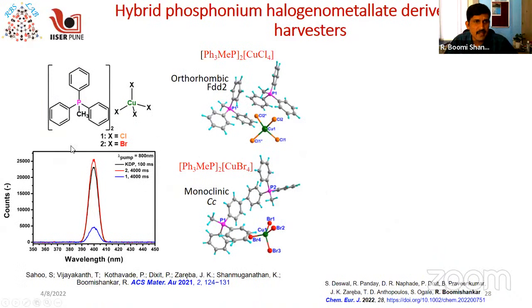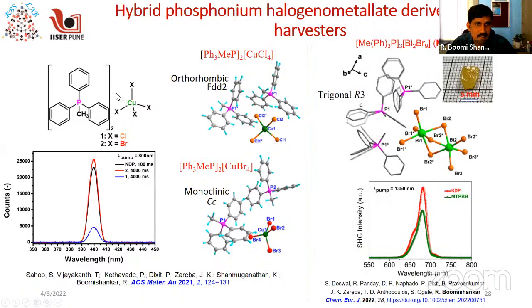and we then tried to use the potential of this system for various other anionic counterparts. So we use the same cation and use different anions. In this case, it's a copper salt, whereas in this case, it's a bismuth salt. So in all the cases, we were able to see very good performance. We can also establish the non-centrosymmetry of the system by measuring the nonlinear optical properties of the system,